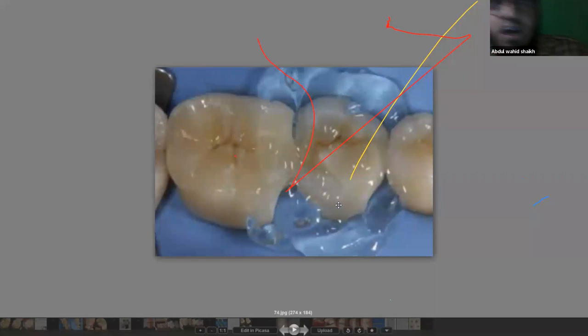And this particular oxygen inhibition layer becomes more important when you are doing posterior bonded restorations. Because when you're doing a direct composite restoration, okay, fine, we can see that the occlusal part or the topmost part is not cured properly, maybe it is not strong. But when you do proper finishing and polishing, you will be able to remove some amount of the topmost layer and get a decent polish. But when you're doing a posterior bonded restoration, the composite that is present is very thin at the interface of the tooth and the prosthesis. It's very thin, so you don't have much scope to remove that.